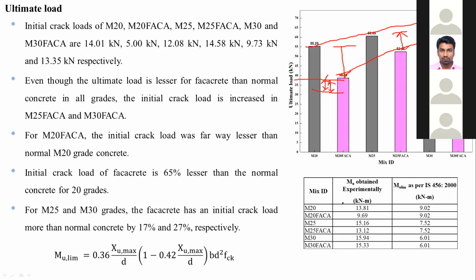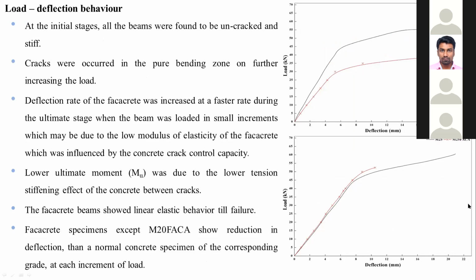We are trying many things, but it is a positive research outcome, because we didn't use any admixtures. It is a pure new material without any admixtures or strength improving factors. We didn't add anything. Next we calculated the load deflection behavior, and we found that all the cracks occurred in the pure bending zone only. The Facacrete beam showed linear behavior up to failure, and the deflection behavior was linear for Facacrete up to failure.